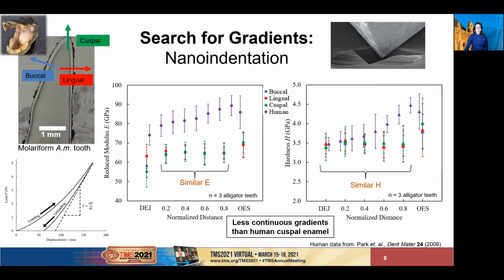As expected, the outermost layer of alligator enamel was significantly stiffer and harder than the rest, with an elastic modulus of 69 gigapascals and a Berkovich hardness of 3.79 gigapascals. But rather than a gradual and continuous gradient towards the DEJ, as is the case in humans, the properties plateau throughout the middle enamel. The average elastic modulus then drops to 59 gigapascals at the DEJ, but the hardness remains pretty constant at 3.47. This sharp property gradient at the outer enamel agrees with our microscopy observations.